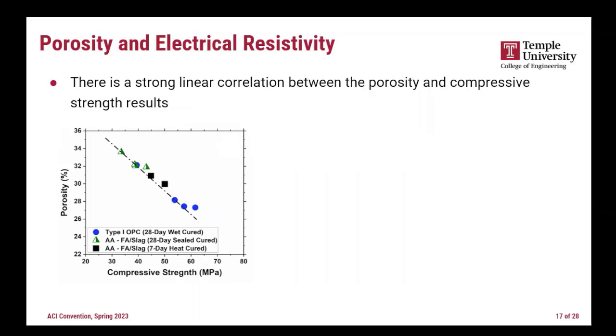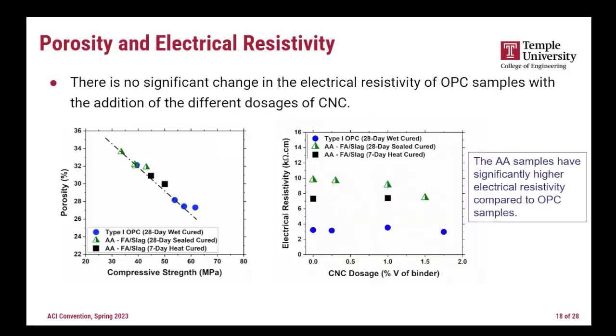We looked at the porosity of this system. There's a strong linear relationship between the compressive strength and porosity. The electrical resistivity, we saw some abnormalities, and we think this is mainly due to the leaching of the alkalis from the reacted and unreacted phases in the system. So that's why we are seeing a higher electrical resistivity for alkali activated versus the OPC.